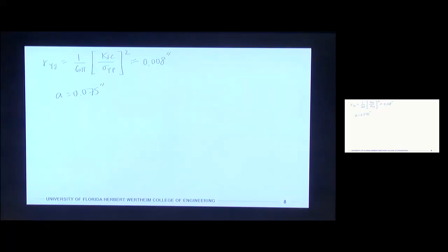So if we take our initial crack size and we add on this plastic zone correction, we'll call it a prime, then we come out with 0.083 inches. So that's what you'll see in the example problem in the book. I wanted to do the simpler case first before we came back and did this one. And so the solution is exactly the same, right? Except now instead of integrating with the 0.075 inches as our initial crack length, we have a new initial crack length of 0.083.